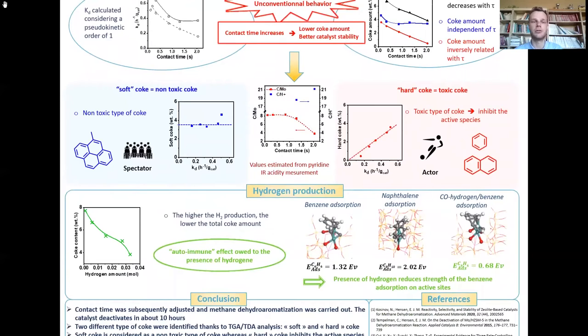On the left, we can see the soft coke and its amount is totally independent of the deactivation constant. This type of coke is made of polyaromatic compounds and is considered as a non-toxic type of coke and is a spectator in the reaction.